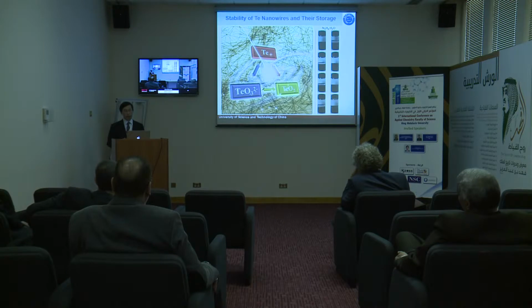That indicates these ultra-thin nanowires, because they have very thin diameter and huge surface area, are very easy to be oxidized even under ambient condition. So that is how we can store these high quality nanowires in the solution. If you store them in water, if you close this cap and keep it isolated from oxygen, you will find that you still can't store them without them being totally oxidized, right? But if you store them in a reducing atmosphere, you keep them longer. So you can keep them even more than 1 month. That's the indication that this kind of structure, we still can store if you choose a different storage method. Because these ultra-thin nanowires are very easy to be oxidized, right?